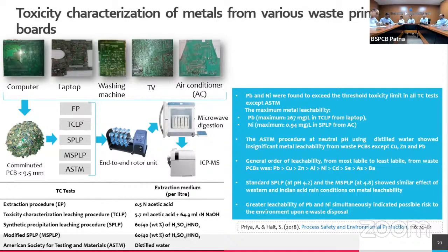essentially lead and nickel are crossing the toxicity limit prescribed by the international agencies, and they are present in substantial amounts simultaneously. Since they cross this threshold, they can induce very severe toxicity, and that's why this e-waste stream is considered a hazardous stream, and we need to treat it as hazardous waste.